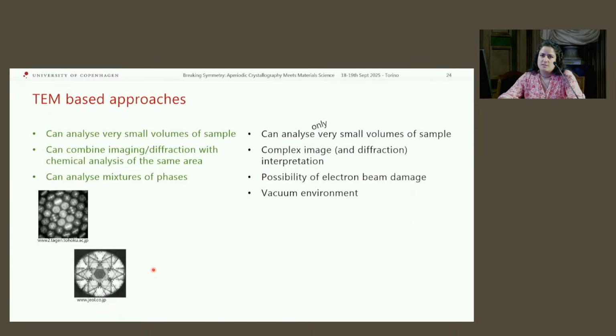So I hope I showed you that with the transmission electron microscope, we can do a very valuable analysis, because we can see the sample, we can determine the structure, and we can do chemical analysis all on the same spot. And also we need a very small sample. On the other hand, the drawback is that we are only analyzing a very small sample, so we have to make sure that it's representative of our bulk sample if we want to generalize, for example, the properties. Then we have seen that because of the experimental conditions, this is not suitable for all kinds of materials due to the vacuum and the high beam energy.